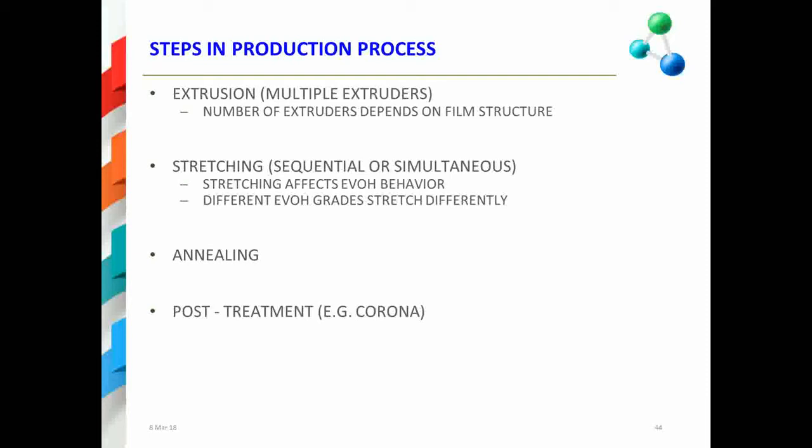This is because different EVOH grades stretch differently, with polymers that contain more ethylene generally stretching easier and at higher stretch ratios. However, it also needs to be remembered that those same polymers do not provide as good an oxygen barrier as do the polymers that contain more of the vinyl alcohol moieties. So there will be some trade-off between the stretching behavior.